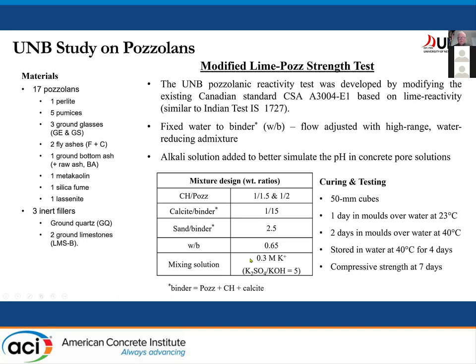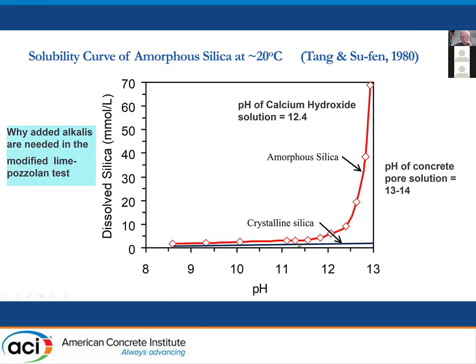And what makes this test work is the mixed alkali solution, alkali hydroxide and alkali sulfate, which raises the pH. And that's really important because the solubility of glassy silica in the fly ash is very dependent on pH. If you have crystalline silica like quartz, it doesn't matter what the pH is at normal temperatures, you're not going to get much soluble silica out of it.